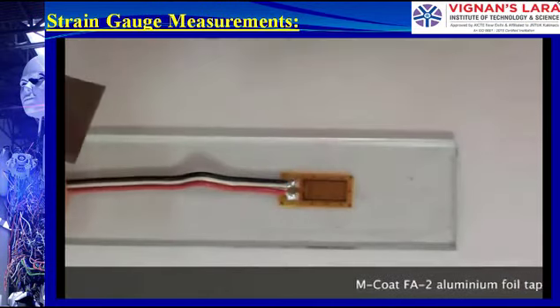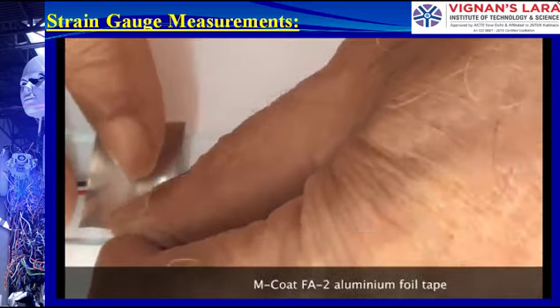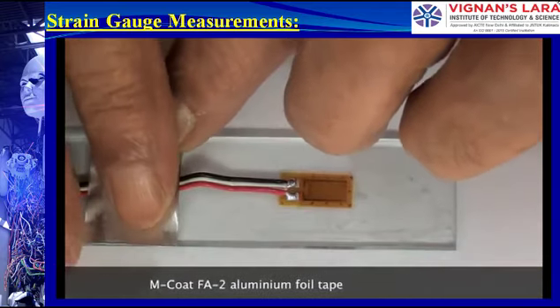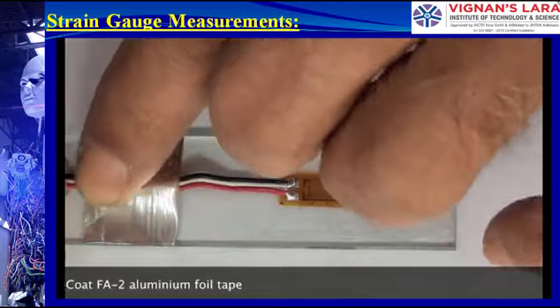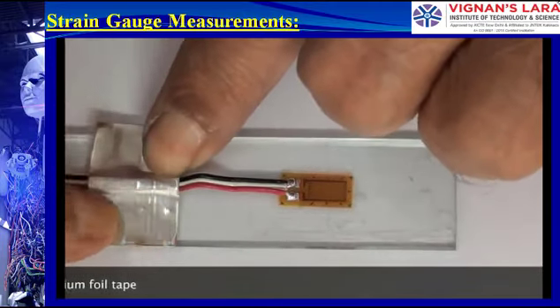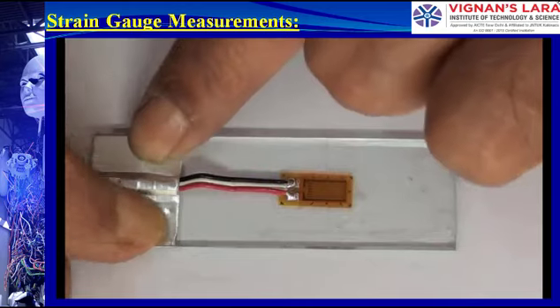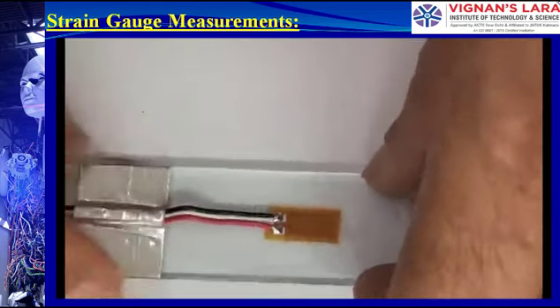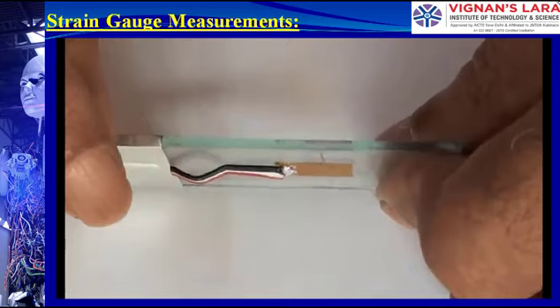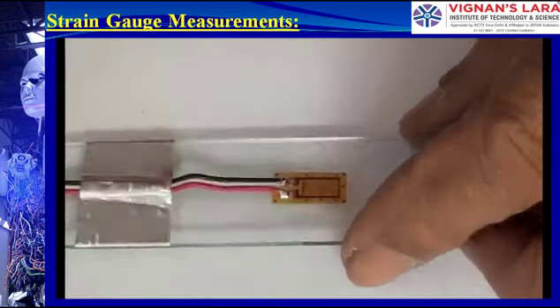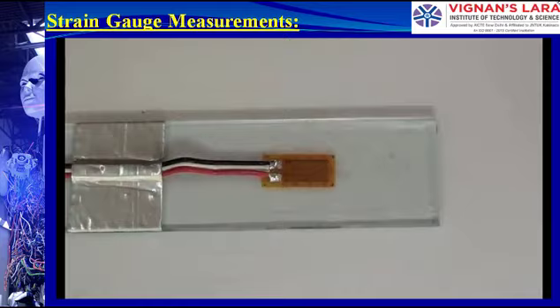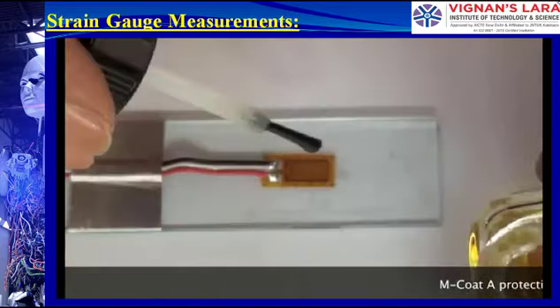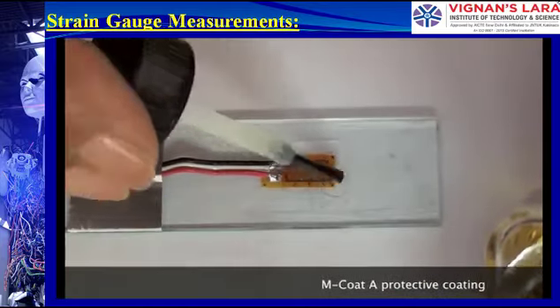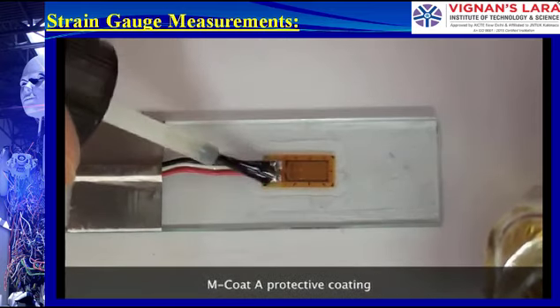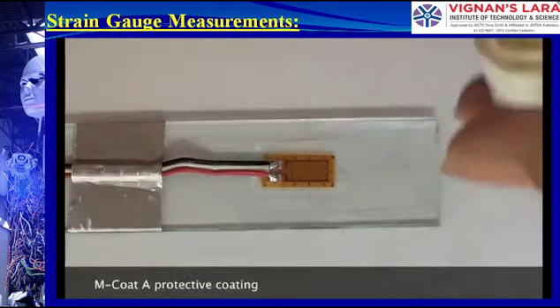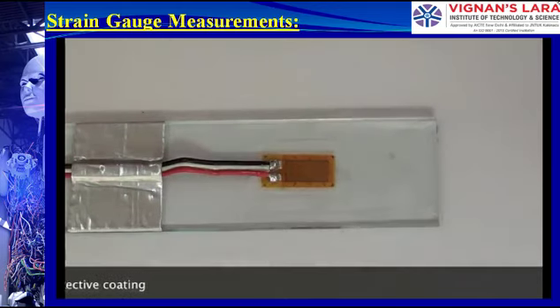The lead wires are then anchored to the test part with Fa-2 aluminum foil tape, which has a strong adhesive backing. The strain gauge and lead wire joints are covered with a layer of M-Coat A protective coating, which is applied with a brush. The coating dries in about 10 minutes and the gauge is ready for testing.